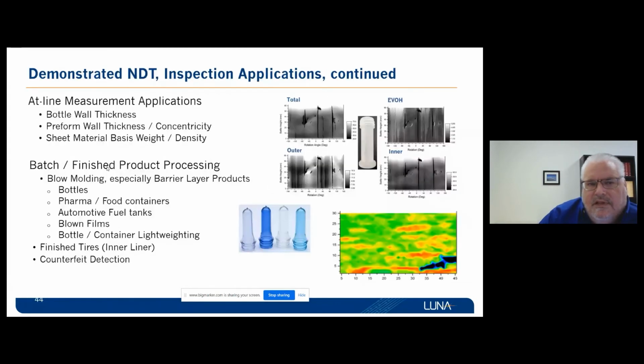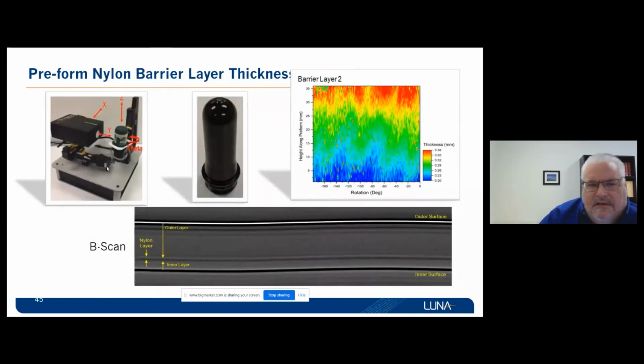Another area is measuring bottle wall thickness, which is very important in reducing manufacturing cost of bottles. Bottles are often made of multiple layers, say two outer structural layers and then a thin layer in the middle that is actually the vapor barrier that prevents gases from ingressing or getting in and out of the plastic, making the true seal. As you can imagine, the manufacturers want to have enough plastic in each layer, but not too much. It costs money.